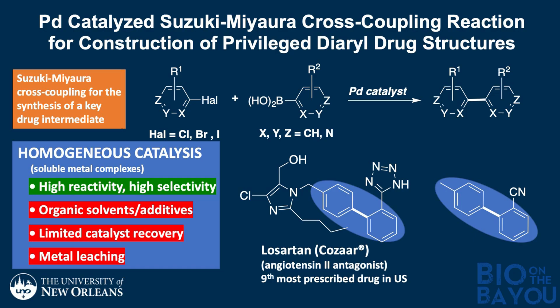Now, these compounds are typically prepared through what we refer to as a homogeneous catalytic process. That is, essentially the metal is soluble in the reaction media. And this is great because it has high reactivity and high selectivity for these reactions. The downside from a green chemistry point of view is that these reactions are done in organic solvents. Oftentimes there's organic additives. That all contributes to the waste of this process. Also, there's limited catalyst recovery. Okay, you can recover the metal, but you're not going to recover the catalyst. And of course, since the metal is soluble in your reaction media, you can have trace metals showing up in your product. So that's going to take you to another step of purification and essentially more waste generated.